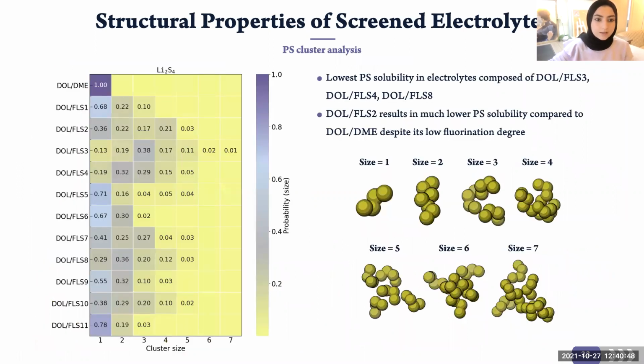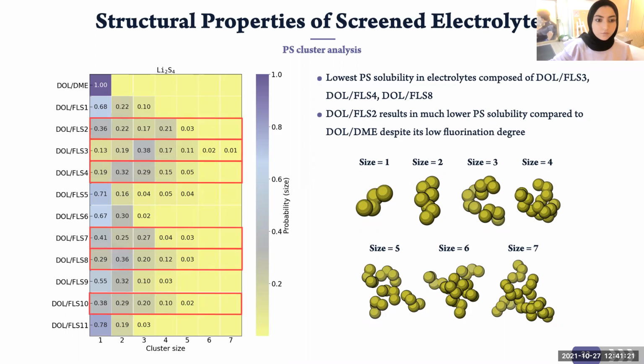And here are the results of the cluster analysis that we performed, where the heat maps show the probability of forming a polysulfide cluster of a certain size between 1 and 7. And this is the probability here for the different electrolyte systems that were screened. And we can see that for the conventional electrolyte, there is almost no clustering of polysulfides seen in this electrolyte, whereas in electrolytes composed of FLS2, FLS3, 4, 7, 8, and 10, there is much higher degree